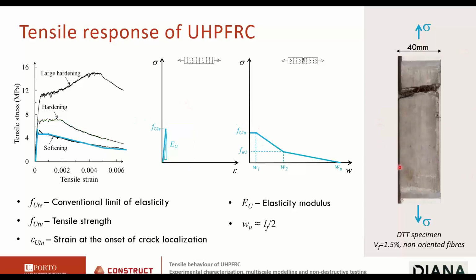So in this case, you see the same mix of UHPFRC, but now with much less fibers, half the fiber content of the previous specimen, so 1.5% only of non-oriented fiber. So what do we see? In this case, the material shows strain softening behavior. So it doesn't have the ability to form the desired array of tightly spaced cracks. So in this case, it behaves as a standard fibre-reinforced concrete, eventually with a higher conventional limit of elasticity, but only one crack forms and only one crack governs the behavior.